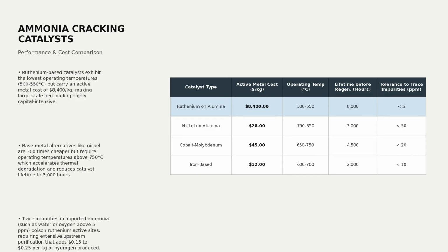Project developers face a stark trade-off between catalyst cost and operating temperature. Ruthenium-based catalysts operate at lower temperatures but cost $8,400 per kilogram. Nickel-based alternatives are 300 times cheaper but require temperatures above 750 degrees. These extreme temperatures accelerate thermal degradation and reduce catalyst lifetime to 3,000 hours. Furthermore, ruthenium is highly sensitive to impurities like water or oxygen. Removing these trace contaminants requires extensive upstream purification. This step adds up to $0.25 per kilogram to the levelized cost of the delivered hydrogen.